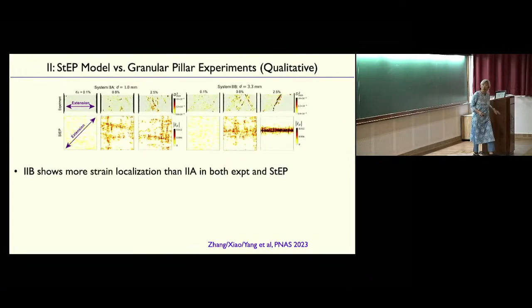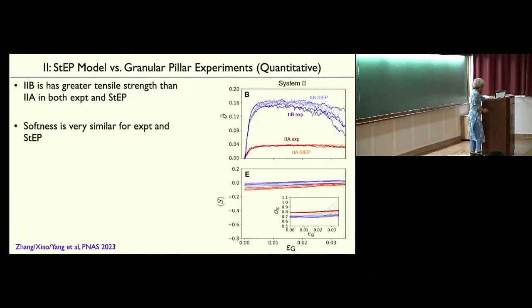Here's the experiments. On the left, the case with less strain localization, the smaller particles. You see, again, plasticity is sort of distributed all around, whereas for the larger particles, it starts to get localized in the experiment, and you also have it localized in the simulation. Quantitatively, it actually works remarkably well.